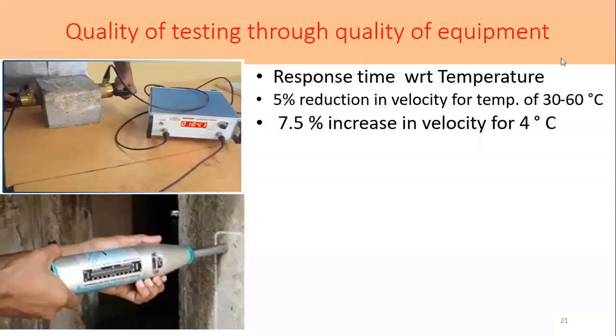Now we are conducting the ultrasonic test even in winter at a temperature of 10 degrees centigrade with the same velocity value. Even if we conduct it in the hot summer, to the tune of 42 degrees centigrade, we consider the same velocity. There is no correction factor, neither on the reduction side nor on the increment side, that we apply. Next, please. So this is hampering the quality of the testing.